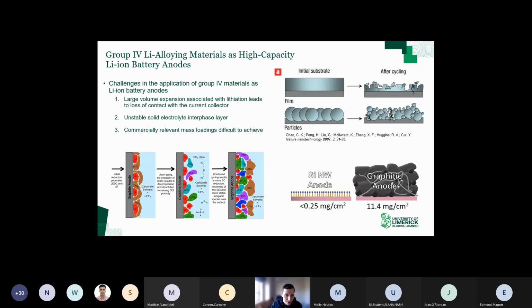Another challenge related to these alloying materials is that it's difficult to get commercially relevant mass loadings. Okay, so you want to be upwards of 1 milligram per centimeter squared for silicon, certainly, and probably even beyond that, so above 1.6 or 1.7 milligrams per centimeter squared if possible. So that is a challenge, getting that amount of material onto a current collector and having it perform stably.